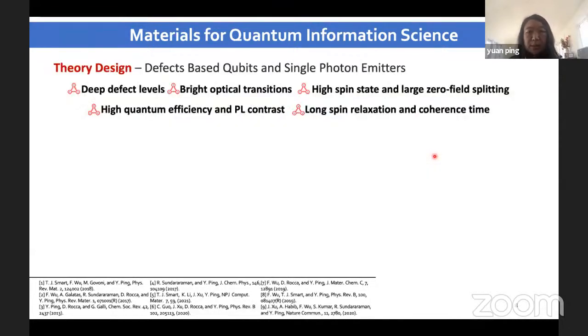So what are the specific material criteria if you want to have a candidate material which can be used as a spin qubit? Here is a list of properties. For example, they have to have deep defect levels. This level will be separated from the bulk, and bright optical transitions, which can be read out by photon, and high spin state and large zero field splitting. This is necessary.